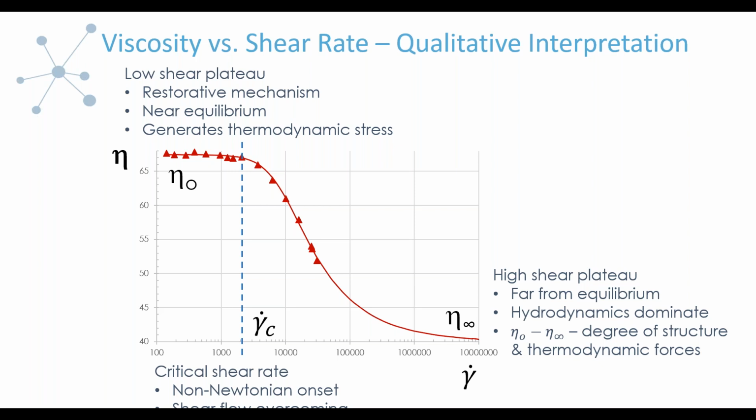So what we're looking at here is viscosity as a function of shear rate. We do have some actual data here, which I've extended with a shear thinning model, the Cross model, because unfortunately we can't get all the way out to the higher shear rate Newtonian plateau. To get this full curve, you generally need many, many decades or orders of magnitude in shear rate. But I wanted to put this on there just so that we could discuss the whole curve.